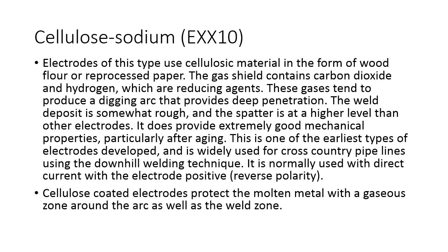Cellulose-coated electrodes protect the molten metal with a gaseous zone around the arc as well as the weld zone. So this stuff, cellulose sodium EXX, is basically burning wood chips or paper, and it's creating carbon dioxide gas around the weld pool. And that keeps oxygen and nitrogen from contaminating our weld puddle. So the gases tend to produce a digging arc, a really deep digging arc that you won't find with other weld materials,